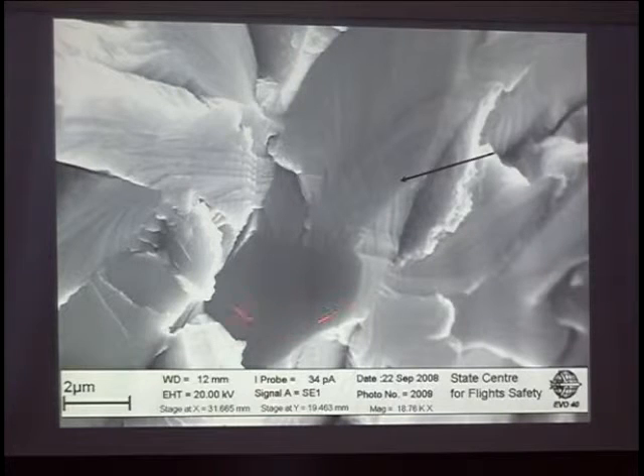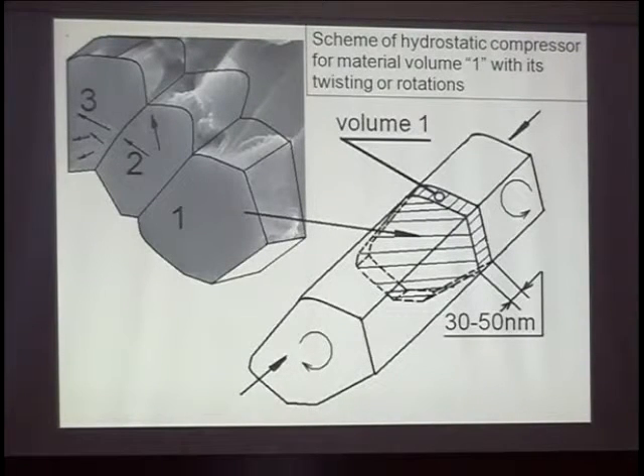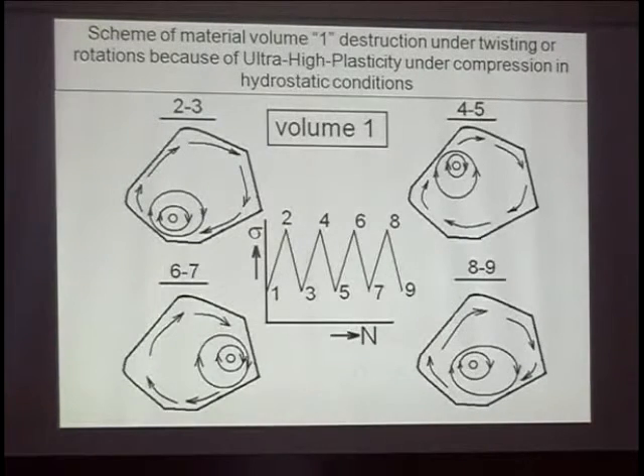and that's why there can be seen, first of all, a flat surface of weak material, and then material cracking in a quasi-cleavage manner around this facet. It is independent of the stress level and depends only on the material state that realizes this type of subsurface cracking. So this is the mechanism or model of the first step of material subsurface cracking, a model that explains material cracking because of twisting in the condition of compression.